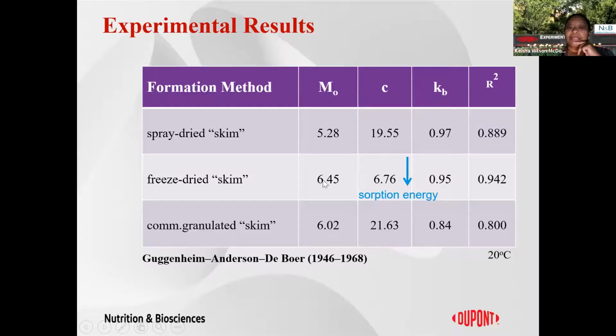One of the things that you'll notice is that the freeze-dried skim milk has the lowest sorption energy. It has the lowest energy constant with the lowest energy absorption behavior, which means that the ability of water to absorb onto this surface is much easier because there's a lower energy barrier. Similarly, you can see that the freeze-dried products also have the highest monolayer moisture content. With easier absorption of water, you have more opportunity for the water to absorb, and so therefore this material would be considered more hydrophilic than the other two.